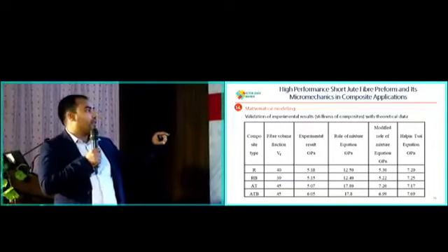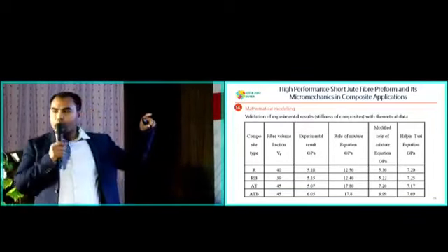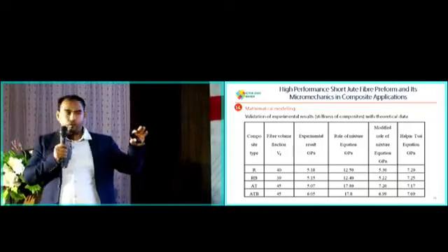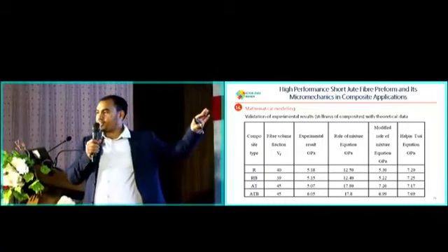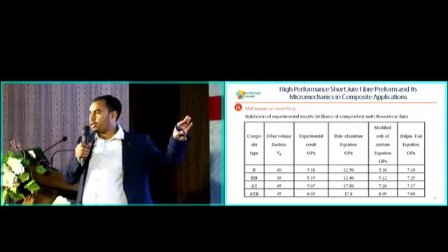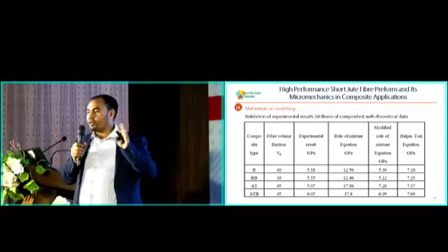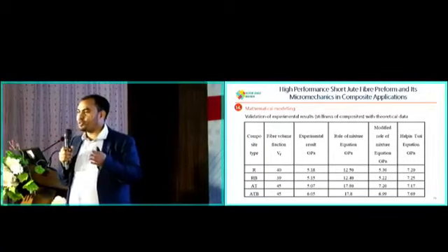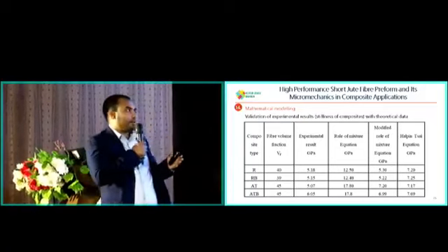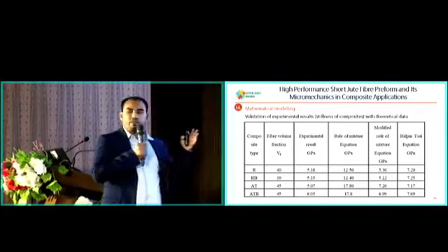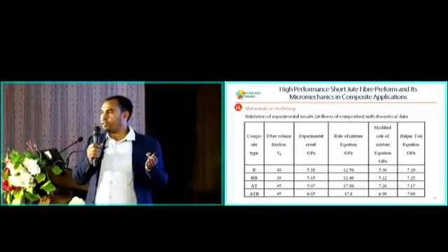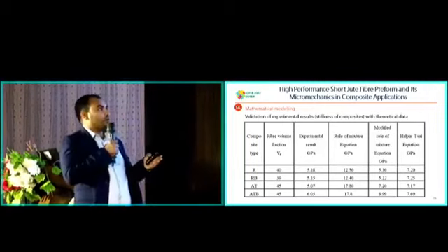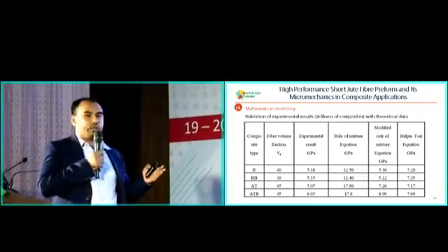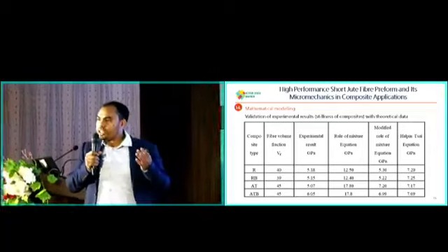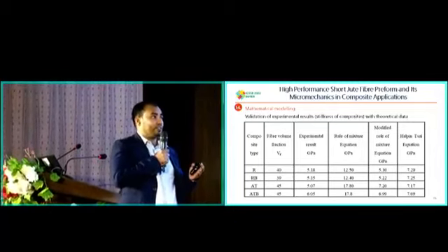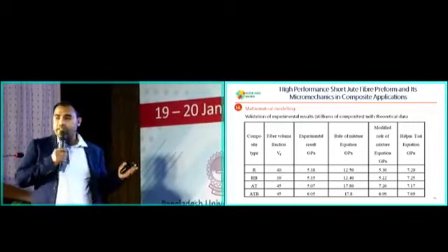Similarly, we adopted the rule of mixture formula. It's the simple formula. As you can see, the data is not well fitted. But we have to check anything in composite material based on the rule of mixtures. So we check straight away what is happening with the equation, and it's not fitted because a lot of variables have not been considered. So we go for the modified rule of mixtures equations where we have considered the orientation factors and length efficiency factors, and it completely fitted the data.